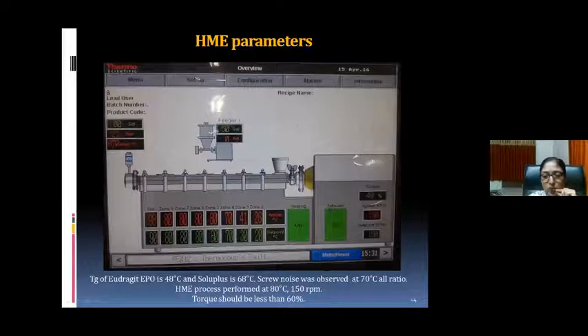Now let us see the working of this hot melt extruder, where you can see the torque, which is generally maintained below 60%. In this case, I have maintained 150 RPM. It consists of different zones from zone 2 to zone 8, where initially the temperature is low. You add the dry mix containing the drug, polymer, plasticizer and lubricant into this hopper, through which the material passes into this cavity, and there are screw elements which help push the material in the forward direction. The initial temperature will cause a slight amount of melting of the drug and polymer mixture, and the screw elements keep pushing the material forward.